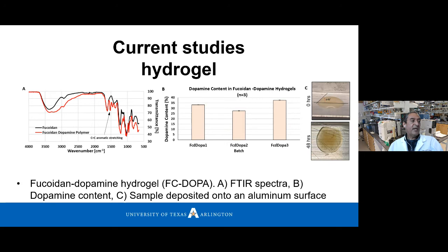And later, after 48 hours, we observe the formation of a film. And in this case, the brownish coloration of the film is evidence that the dopamine contained in the hydrogel is cross-linking. In other words, it is reacting and forming links to adhere between the dopamine molecules and also to the aluminum molecules on the surface.